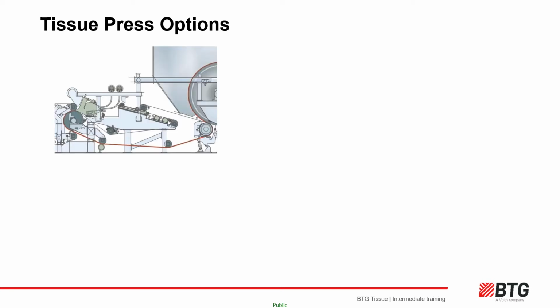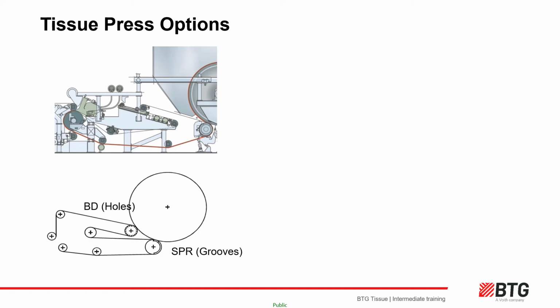In LDC we generally see three types of press configuration. The suction press roll, which dewaters and presses the sheet through the felt and onto the Yankee at approximately 40% consistency at the nip. A double press configuration comprising a standard suction press roll followed by a second press or a blind drill press, meaning the sheet is pressed twice through the felt onto the Yankee. A double press is particularly effective for producing low bulk products.